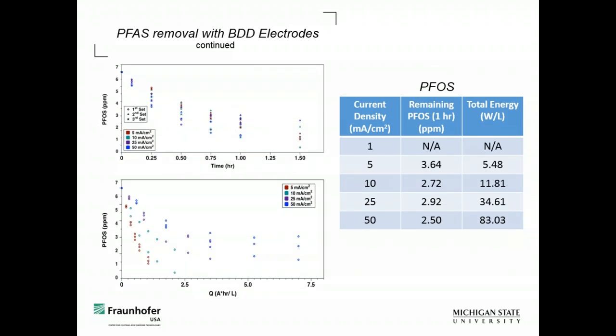PFOS, we did the same thing, but we found that 10 milliamps per centimeter squared was actually just as efficient as 50, so we didn't really go through this whole rigmarole of mixed current densities, combined current densities. So really what we've moved forward with now is we either apply 10 milliamps per centimeter squared for our treatment, or we do our combined 50 and 5.